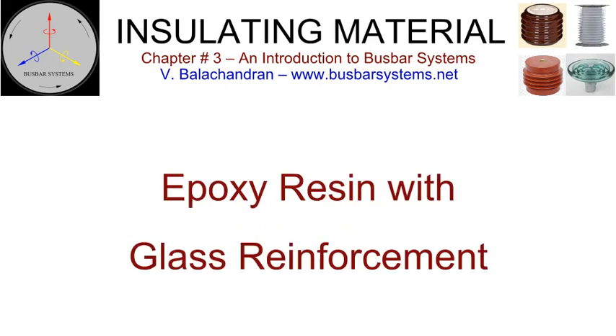Glass reinforced epoxy resin. Glass has been used as a reinforcing agent in epoxy resin components to significantly improve mechanical strength. Depending upon the shape of the component, the mechanical strength of the epoxy can be enhanced several times by reinforcing it with glass. There are various methods of reinforcements, depending upon the shape, size, and application of the product. Hollow cylindrical or conical components can be made by filament winding. Filament wound cylinders are used as housings for the composite insulators, transformers, bushings, outdoor instrument transformers, and lightning arresters.